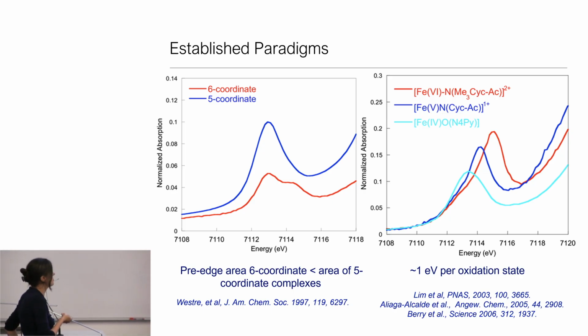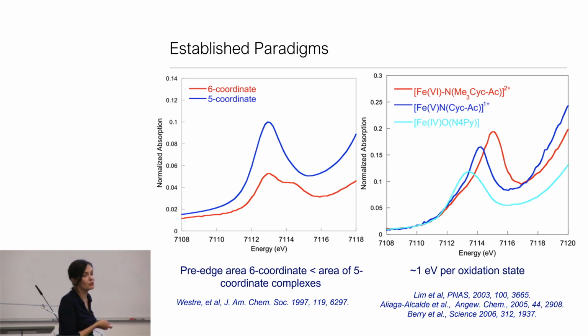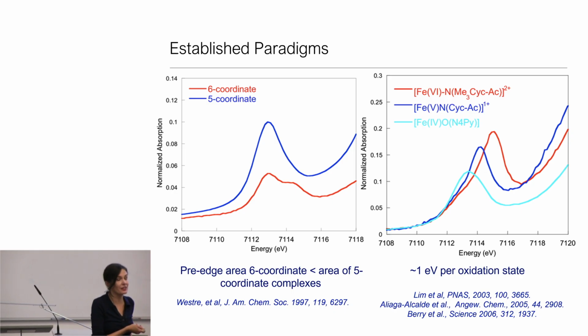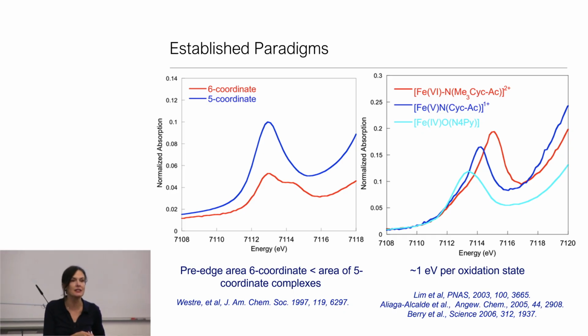The other standard metric that's often in the literature is that pre-edges shift by 1 eV per unit change in oxidation state. So this is an example of iron 4, 5, and 6, published some time ago with Karl Wieghardt's group and John Berry, who's now at Wisconsin, who was a postdoc at the time. And this is just a very nice series. I should point out that very recently with Karsten Meyer's group, we also have identified an iron 7 that still basically continues to fall on this line. So these are unique and very cool examples.